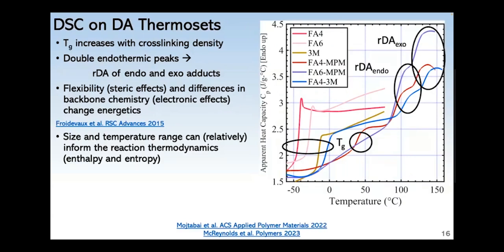And so now I'll show you some generic thermal characterization I performed on the DA thermosets, and these have already been mostly cured. I used differential scanning calorimetry, or DSC, for this. In the plot, I have the heat capacity against temperature, and I've plotted the prepolymers, which are the first three, Fa4, Fa6, and tris-maleimide, and then the full Diels-Alder thermosets, Fa4 MPM in red, the Fa6 MPM in purple, and the Fa4 tris-maleimide in blue.